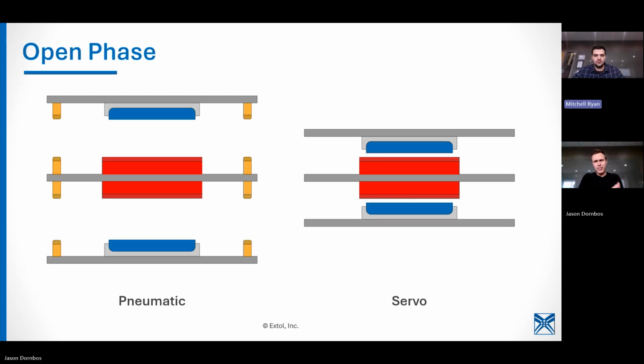Then when we go to the open phase, we're pulling off the heated tooling and trying to get it out of the way as quickly as possible. With a pneumatic welder, you have to open it all the way, and it moves slower, whereas servos are fast, and you can minimize the amount of open so we can bring the parts back together quickly. This is important to what Mitch was saying earlier. Some materials cool off and skin over really quickly. By minimizing the open time, we enable hot plate welding of those materials, where in some cases a pneumatic welder literally can't weld that material. You pour a bunch of heat into that plastic part, and by the time you open, remove the heated tool, and bring them back together, there's a skin on the surface, and you've got a cold weld.